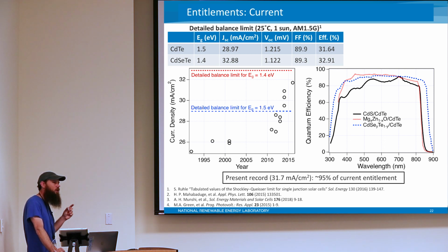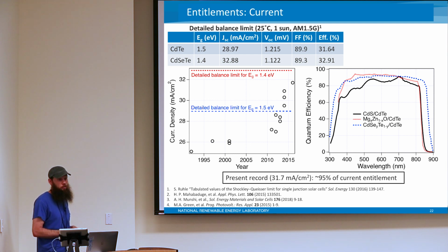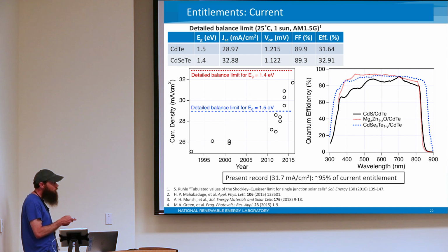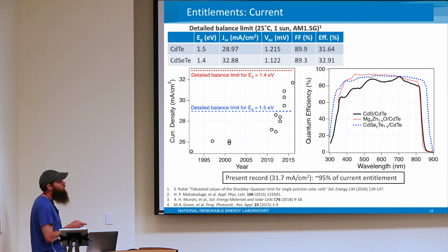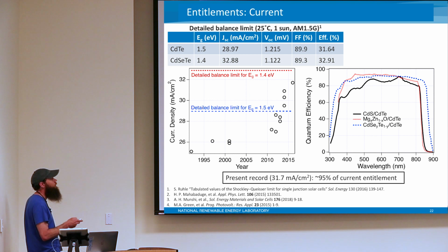So it will actually absorb light, and you'd think, well, it's a semiconductor, who cares? But it turns out that it's fine as an N-type conductor, not so good as a P-type. You get the wrong carriers in it, you lose them. So we're losing current in that. So we actually want to thin it down as much as possible, remove it if we can. And then you can also see fringe patterns from the TCO that we grew on this device.